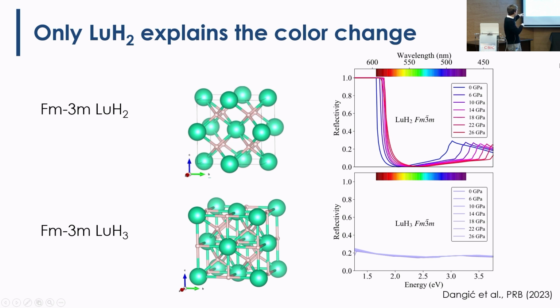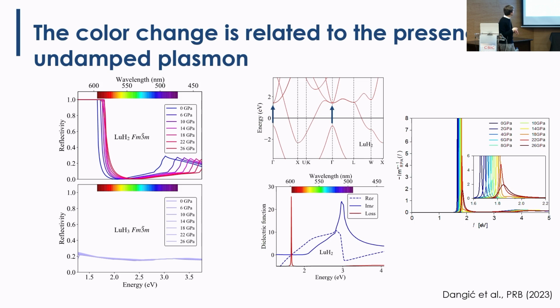On the contrary, this one is gray. So this one has nothing interesting in the color, lutetium H3, nothing. So this is the reason. You see, this is the plasmon that I was referring to, okay? It appears because there are very intense interband transitions in the bands around 2 electron volts. So therefore, this gives rise to an undamped plasmon.